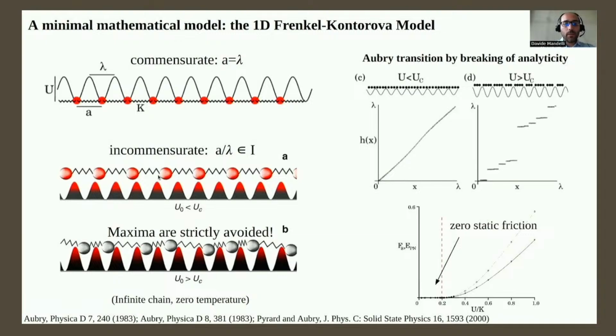structural phase transition. I will not go into the details of the mathematics. I will just point to the main structural feature of this structural phase transition. That is the following. While below the critical corrugation, the probability of finding a particle arbitrarily close to the maximum of the substrate potential is always finite, this probability drops exactly to 0 above the critical point. So maxima are avoided and all the particles tend to condense within the minimum of the substrate potential.